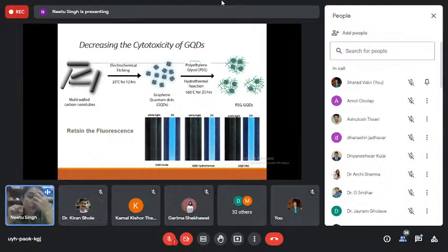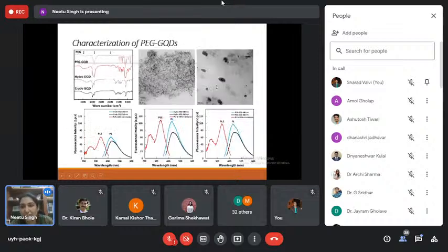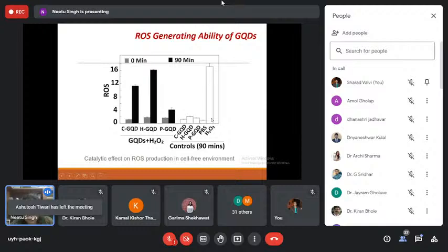Okay. So we thought, can we make a bag and put our nanoparticles inside them so that there is enough polymer, the nanoparticles are dispersed freely, they still maintain their quantum behavior. Okay, so that's exactly what we did. Again, I'm going to skip the details of it. You can read our paper if you're interested. Basically, this is what they look like. This is like an elongated structure with a lot of nanoparticles embedded inside them. The photophysical properties were retained, so they were fluorescent.